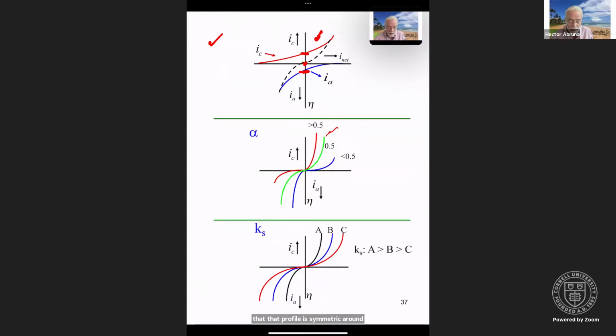On the other hand, if alpha is bigger than 0.5, inherently, what are we saying? We're saying that a larger fraction of the free energy difference caused by the change in potential is driving the reduction reaction. And so you'll see that for the same overpotential, the current here is much higher than the current here. And that's because a larger fraction is going for the reduction.